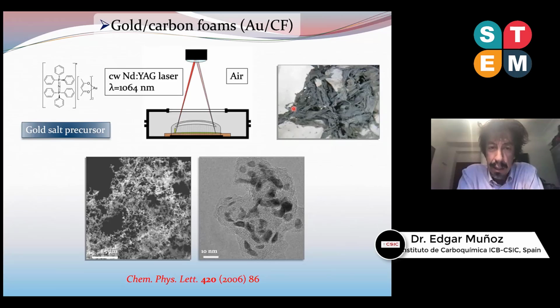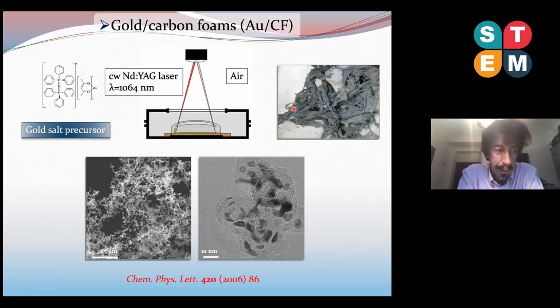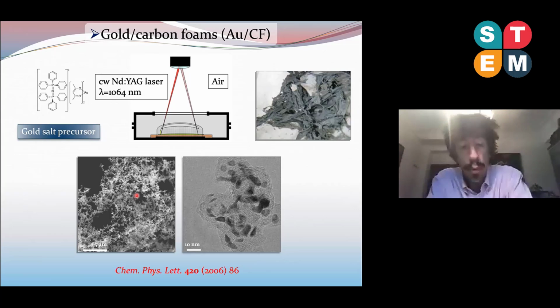So we were excited because we were producing carbon nanotubes in air instead of just working under argon or protective atmospheres. And we were using a molecular precursor, which was very interesting, instead of a hydrocarbon gas or graphite, like we did with carbon nanotubes. So when we did electron microscopy characterization, we observed we produced this kind of spongy-like material. And when we did TEM, we observed this material actually consisted of gold nanoparticles embedded within carbon matrices. So it was not carbon nanotubes, it was a different material. And because of this spongy-like texture, we decided to call this material gold carbon foams or gold carbon nanofoams.